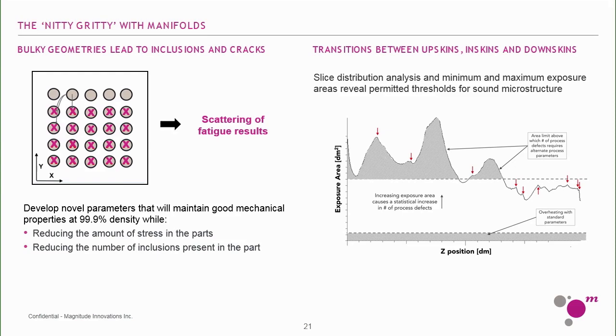And then you have this area above that where the statistical defects increase, because every time you're exposing something, the splashes are going onto another region of the part, and the properties of the final part will actually go down. And then the next thing that we look at is where the area in the exposure changes from one layer to another, because that results in volume jumps.